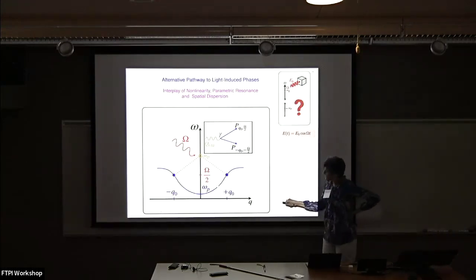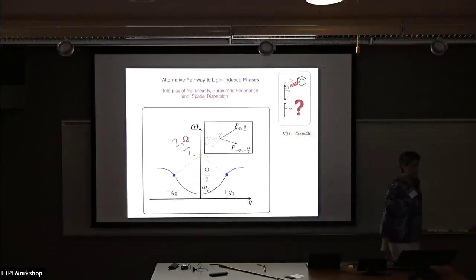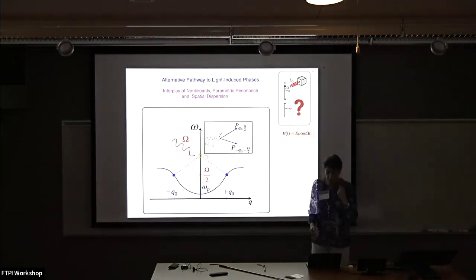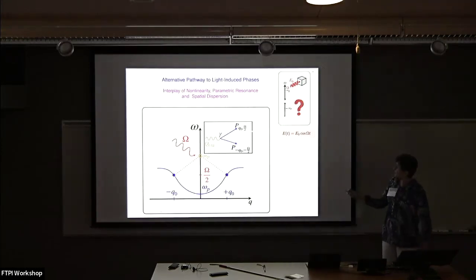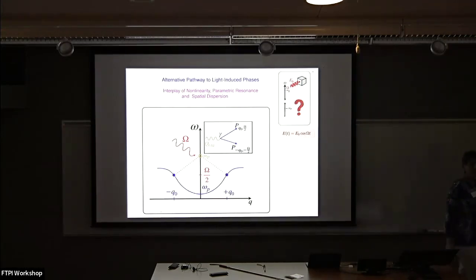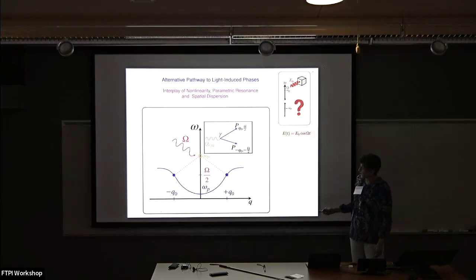And because of the dispersion of the low frequency mode, I will get a modulation at some finite Q vector. And the modulation will be tunable by changing this driving frequency. Now, the onset fluence for this will be determined by the width of these modes. Now, if in fact I get this mode at Q0 and omega over 2, then due to nonlinear self-interactions it can actually generate higher order modes, and in fact, it generates a static mode at 2Q0.